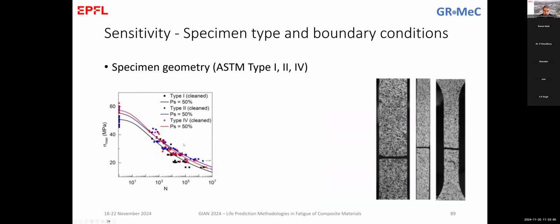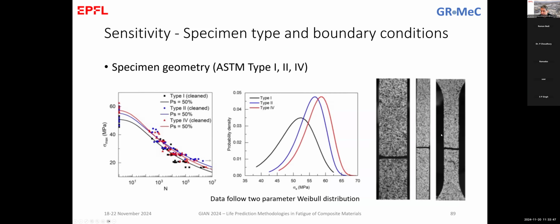So, as I said before, we investigated the effect of the three different types. This is specimen type 1. This is specimen type 2, so the same length of the specimen but thinner. And this is specimen type 4, which is the same thin as type 2, but shorter. And we did a lot of fatigue testing for this. We talk about data sets where we censored all the specimens that failed at the tabs. So we only kept what we call the good failures.